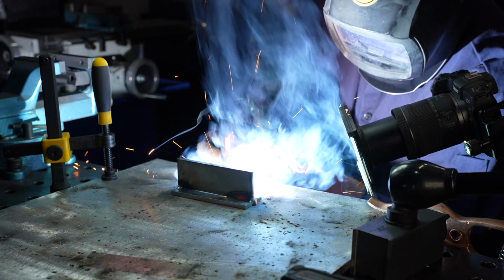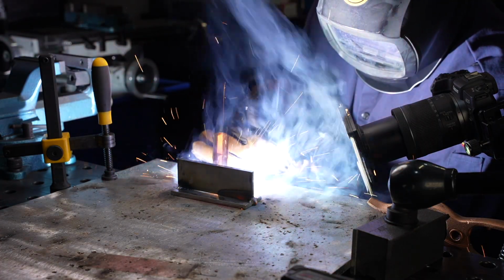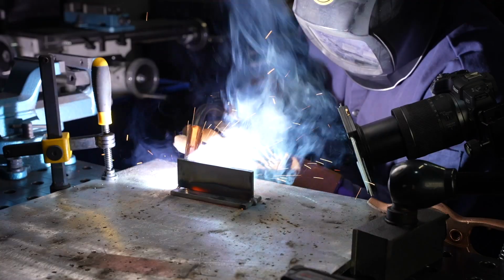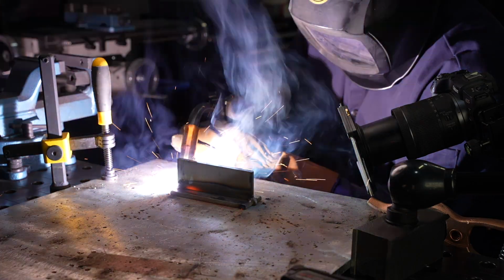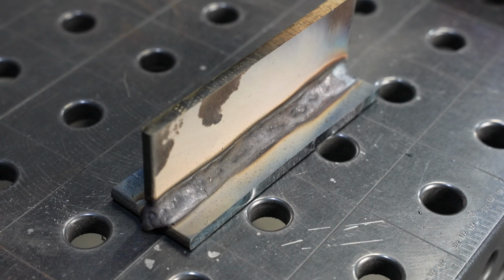Now, notice I'm using a slight drag angle here. This is debated, and let me know in the comments if you run a lot of dual shield, what you do. A lot of people actually run a push angle. I'm kind of in the if there's slag, you drag camp, but the slag is so light in this case that you can often run a push angle, and it seems to do okay. But either one, you just don't want to get too carried away with, and run it nice and consistent all the way across.